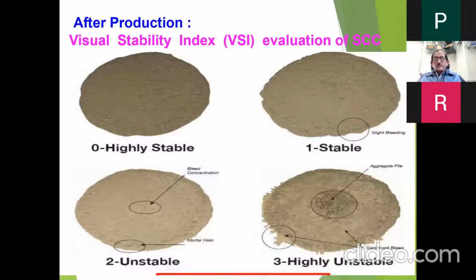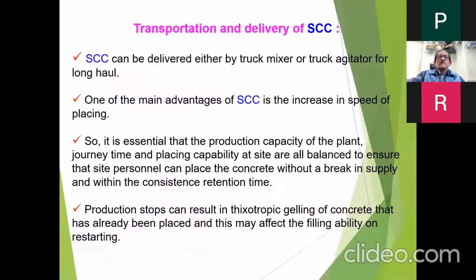After production, the concrete has to be checked for the visual stability index, VSI. The first, with a value of 0, is highly stable. One is stable, with slight bleeding at the edges. Then unstable, with bleed concentration at the center, and mortar is also getting separated, as you can see. And the value 3 is highly unstable, wherein there would be segregation at the center and significant bleeding, water bleeding as well as paste bleeding.